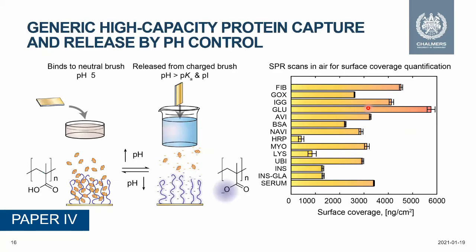So in paper 1, I discovered an attractive interaction between proteins and polyacidic brushes like polyacrylic acid and polymethacrylic acid under acidic conditions. At low pH, these brushes are neutral but protonated, enabling them to hydrogen bond with molecules that they are exposed to through the carboxylic acid group. PMAA is known to form hydrogen bond complexes with other synthetic polymers in solution. And in this case, PMAA immobilizes significant quantities of protein at a relatively high value of pH 5.